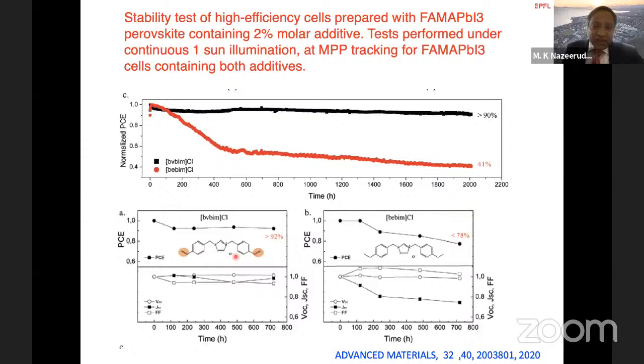On the left side, the ionic liquid has double bonds, which immediately get polymerized at high temperature, at 150 degrees. If you don't have double bonds, it will not polymerize, but it's a similar ionic liquid. Now, if you look at the stability data with the ionic liquid, this remains over 90% stable compared to the reference sample.